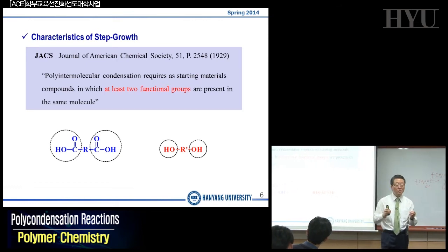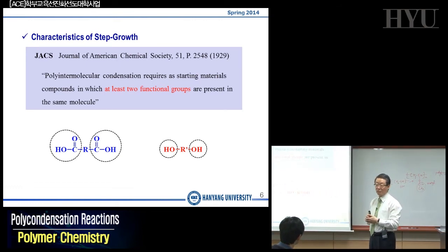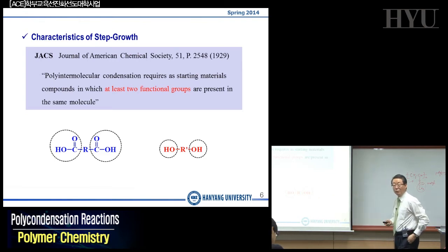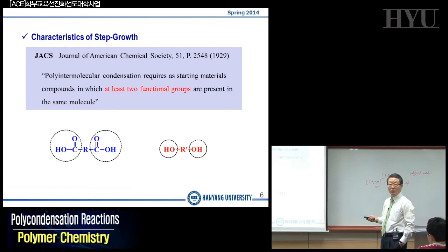If you have those conditions, then you do not have any further polymerization reactions. So this is a particularly good way of determining your molecular weight. In other words, by changing your molar content, you can calculate the exact molecular weight by knowing the molar content. Okay? However, if you have equimolar contents of the 2 monomers, your molecular weight will be infinite. Okay, principally, basically, or theoretically. Anyway, we will talk about this aspect, controlling the molecular weight, later on.